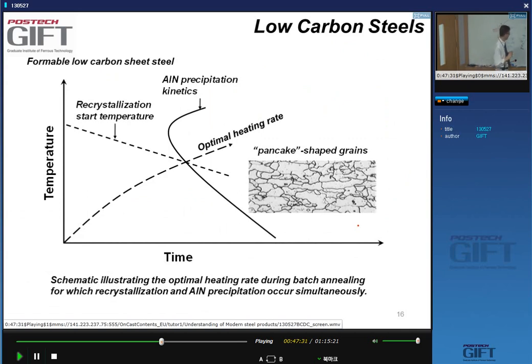So remember that the low coiling route is for the batch annealing route, yes? You keep the aluminum nitride in solution, and the reason is that when you do the batch annealing, you have an interaction between the recrystallization and the aluminum nitride precipitation. And the batch annealing furnace with this very slow heating gives you an ideal heating rate so that these two processes of aluminum nitride precipitation and recrystallization interact. And you get these pancake-shaped grains which have a 1-1-1 parallel to normal direction texture and a good formability.